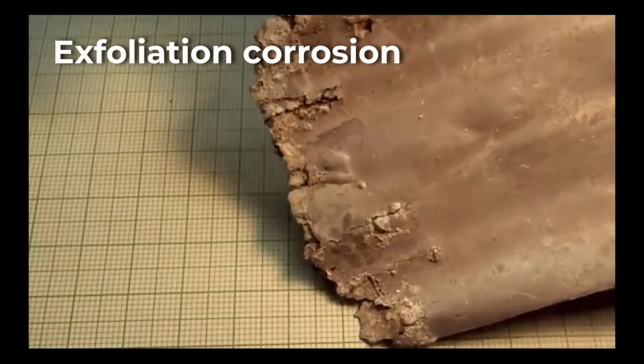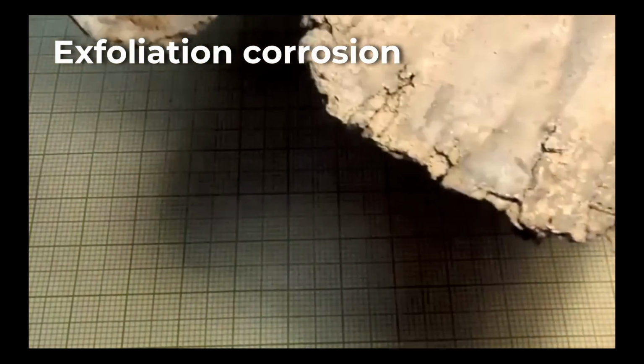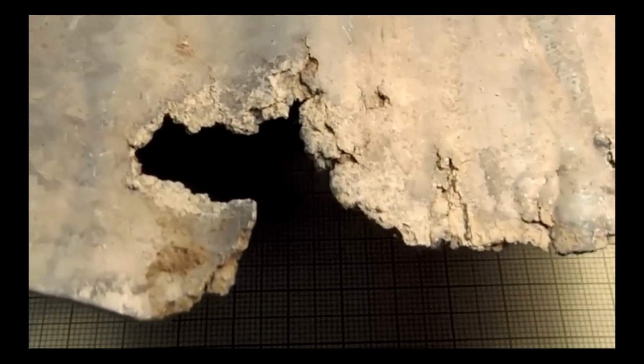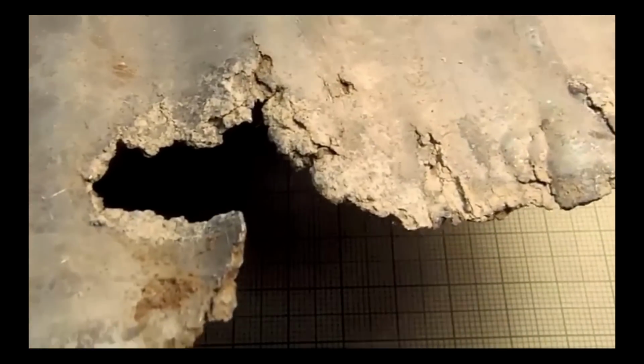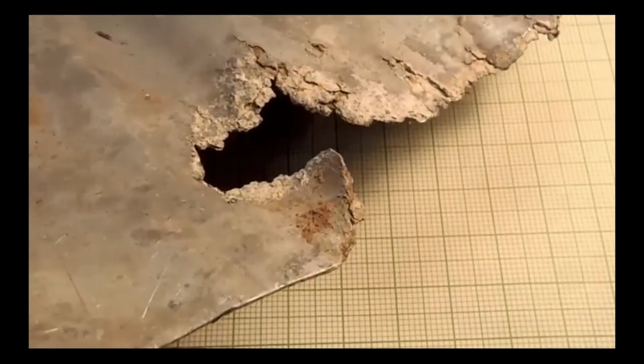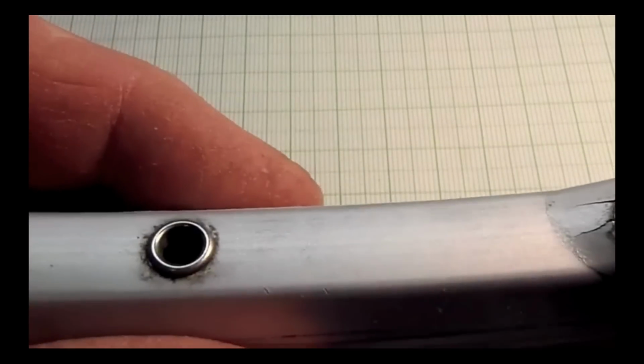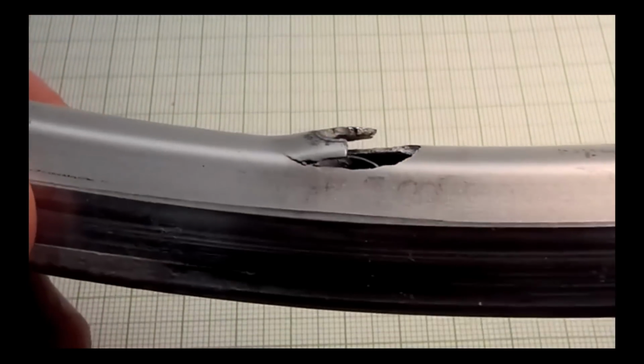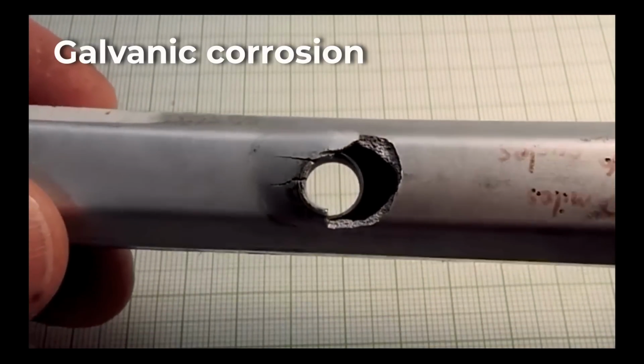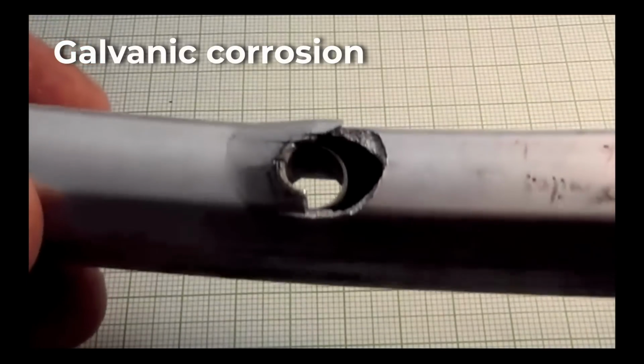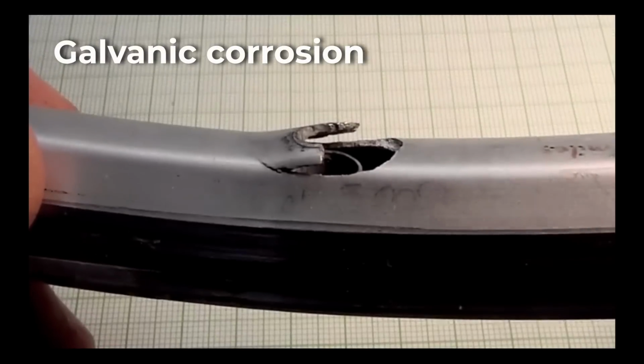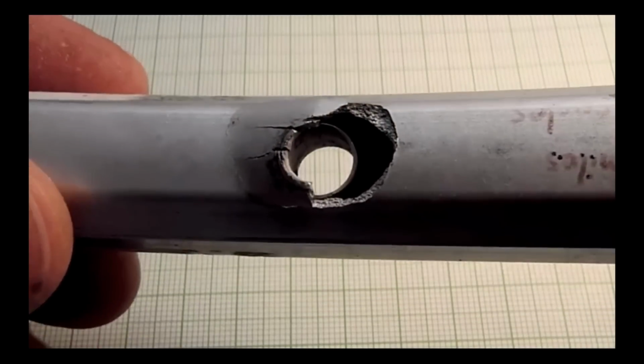This was in ground contact. The ground was very salty. You can see how the corrosion went up between the grains. There are very flat grains that caused a kind of exfoliation, or leafing out. And this spoke right here in the very middle pulled out due to fatigue. So we had an example of galvanic corrosion with the rim, and then also corrosion fatigue causing failure.